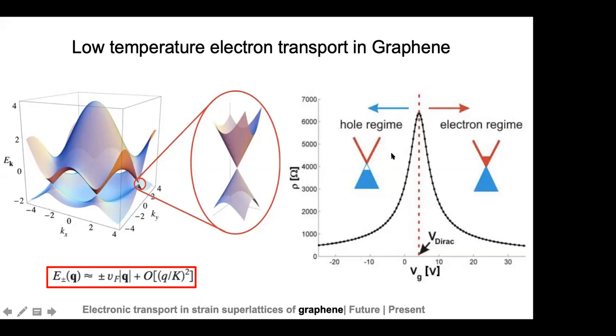Beyond the Dirac point, the Fermi level now lies in the conduction band, which starts filling up, and there are more states readily available to the system. So the resistivity again goes down. If you look at the resistance of graphene, even before considering superlattice effects, as a function of gate voltage, you'll see this sort of a peak, and the peak is at the Dirac point. The conductance obviously is going to be the opposite of this, so it'll be like a V-shaped curve.